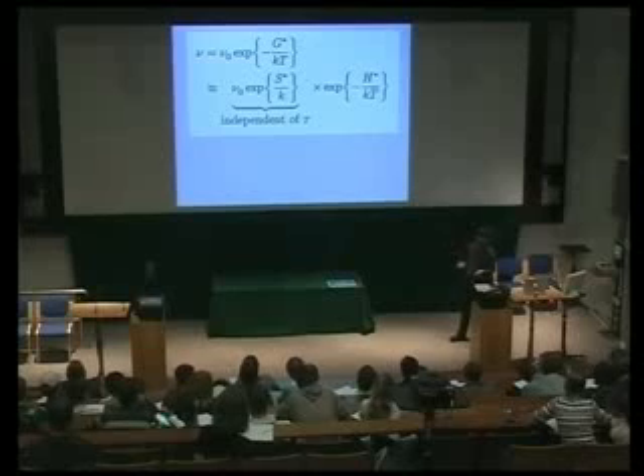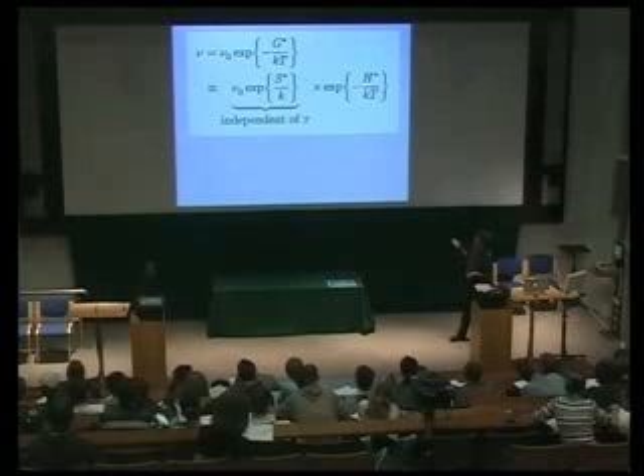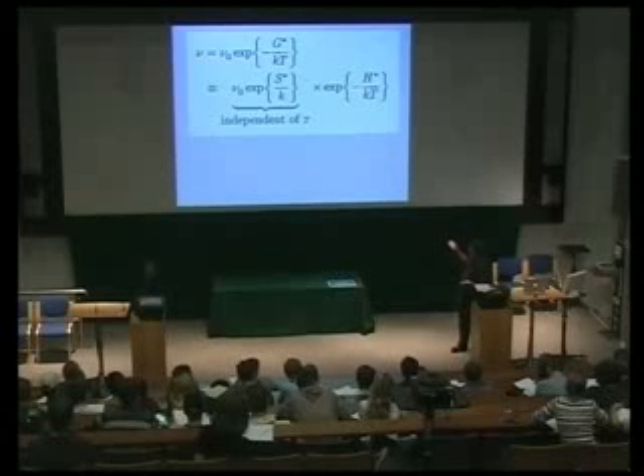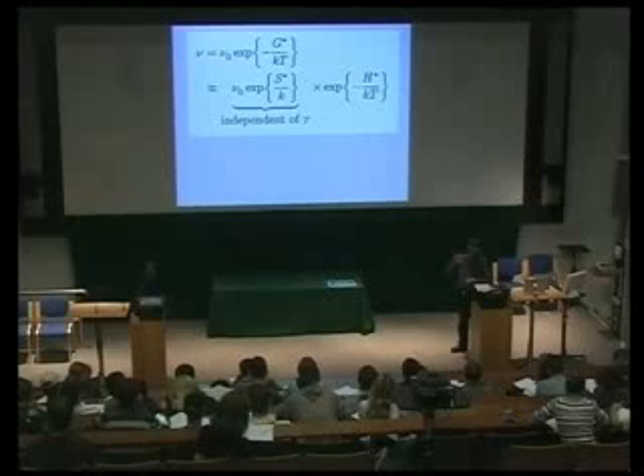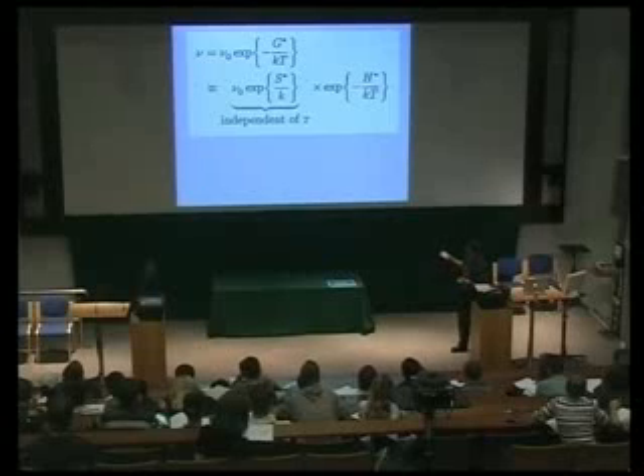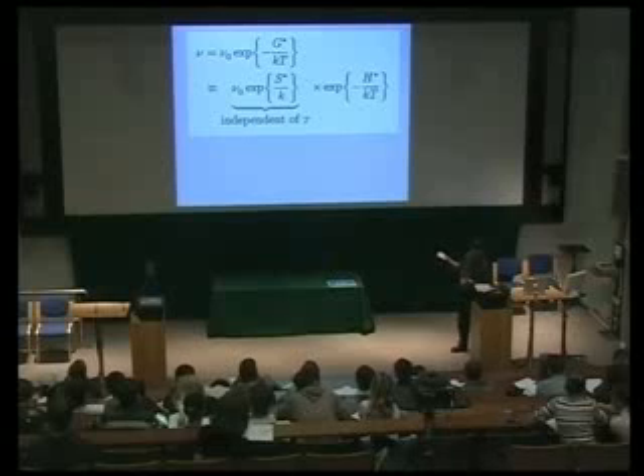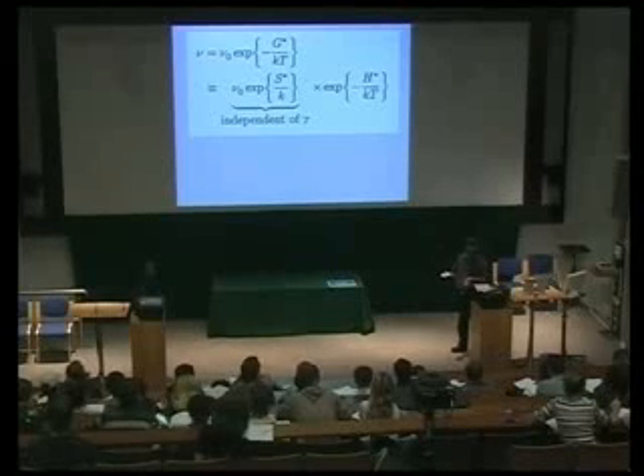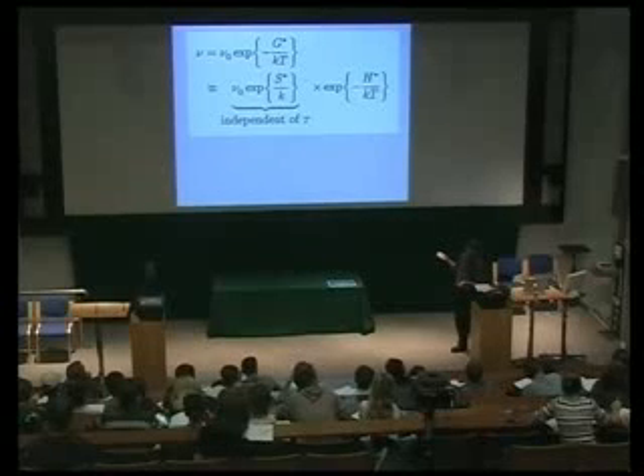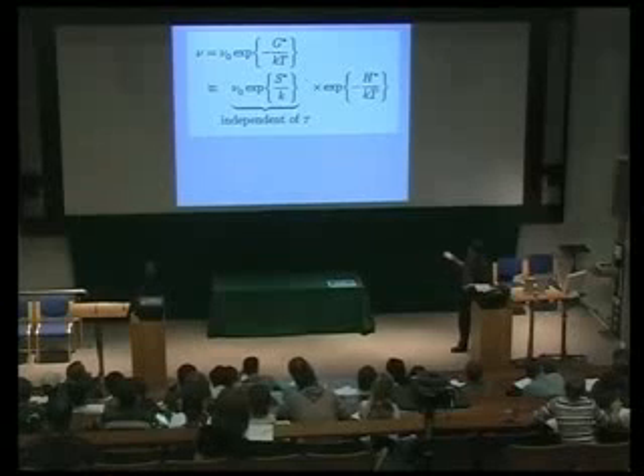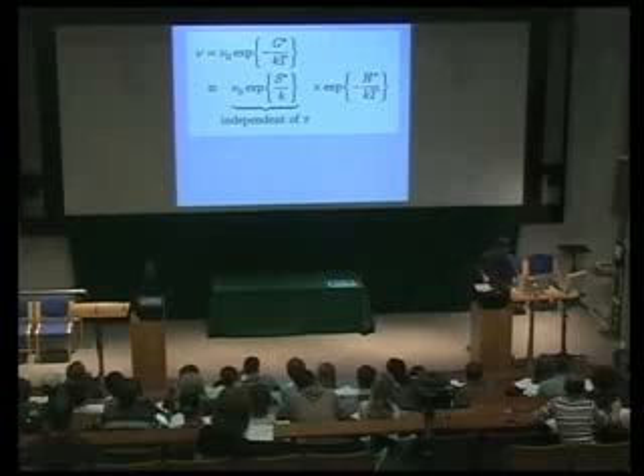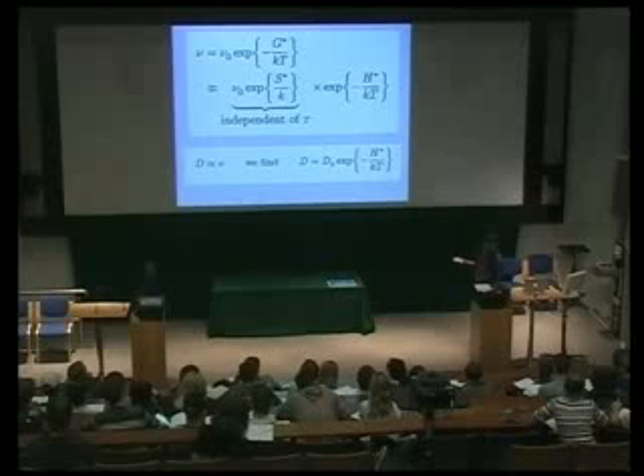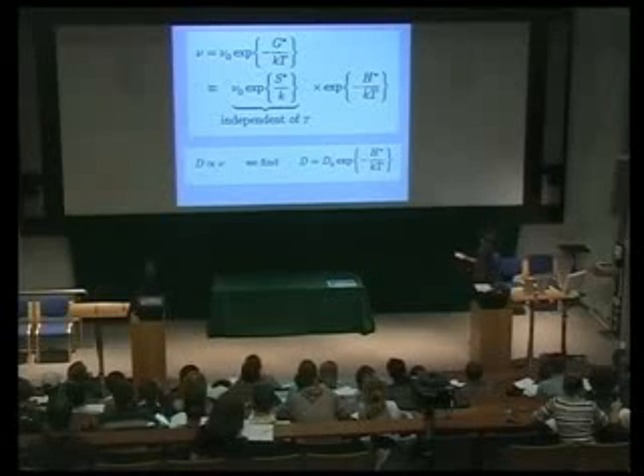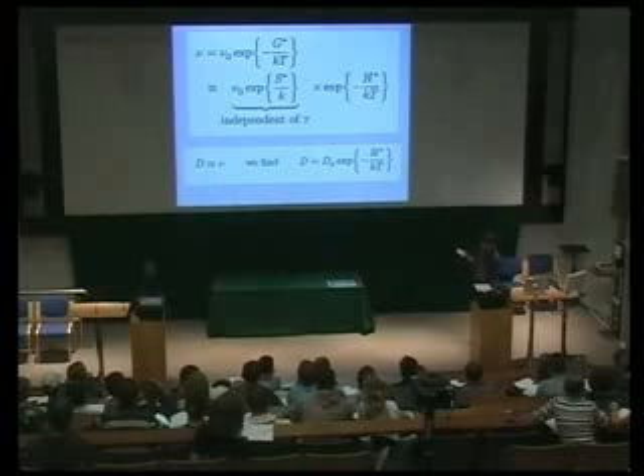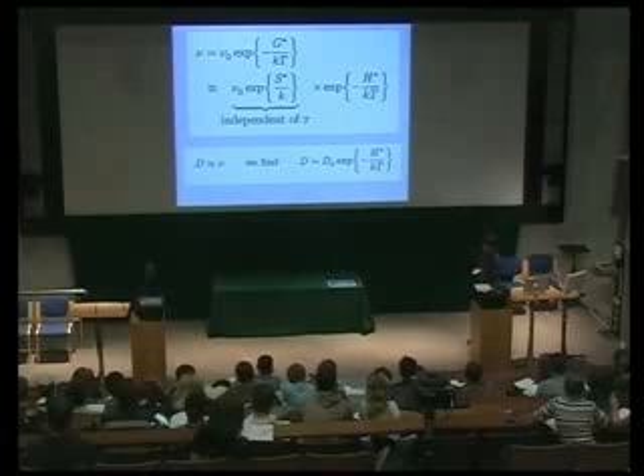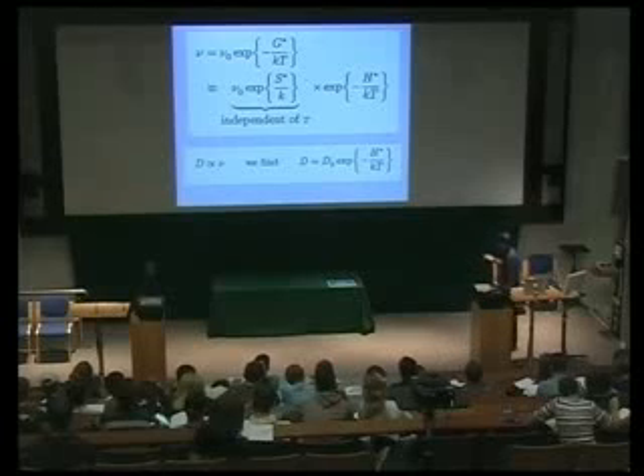I can expand that activation free energy into an activation entropy term and an activation enthalpy term. And in the books, they usually write this as Q, an activation energy. But what they mean is an activation enthalpy, and this part of this relationship is independent of temperature. You know that G is equal to H minus TS, and that's why T has disappeared from this side of the equation. So this is independent of temperature, and this is temperature dependent. And given that the diffusion coefficient is proportional to nu, we can write the diffusion coefficient as D naught, which is the temperature independent term, times the temperature dependent term. So this is the classical way in which diffusion coefficients are expressed.